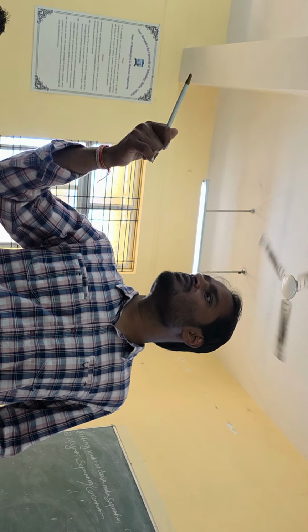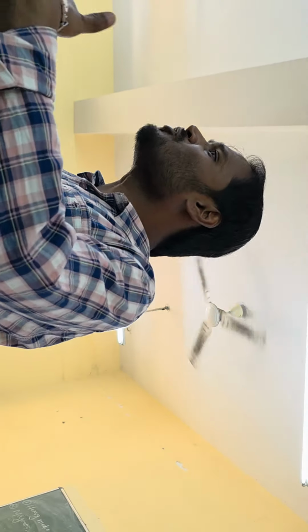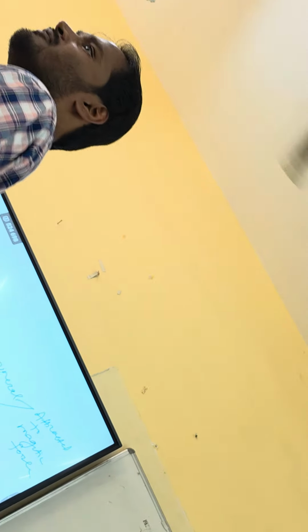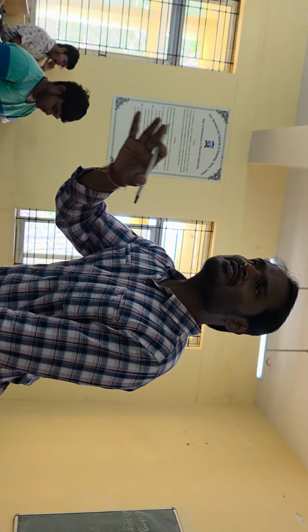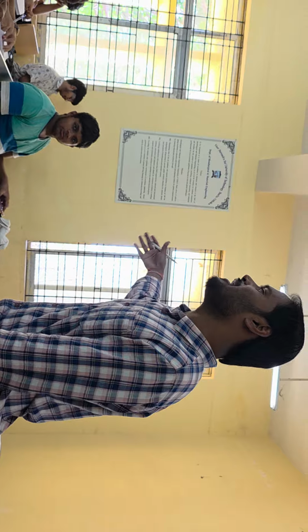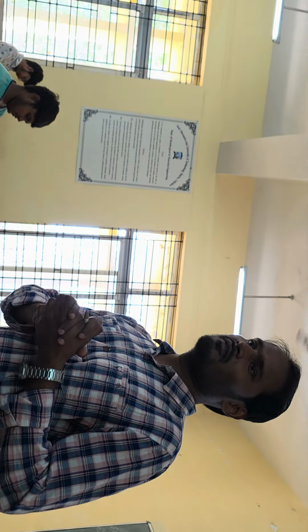FeCr2O4. Very good. Okay, fine. FeCr, right? It's right. Chromite is an ore of chromium, but still iron is there, right? So it automatically becomes paramagnetic because of the presence of iron. Listen carefully, this is very interesting. Chromite is an ore of chromium, but iron is also with it. So that's why it becomes paramagnetic in nature. And that means when you are mining chromite ore, silica will also be there, quartz will be there. So you can separate the quartz from the main chromite ore.